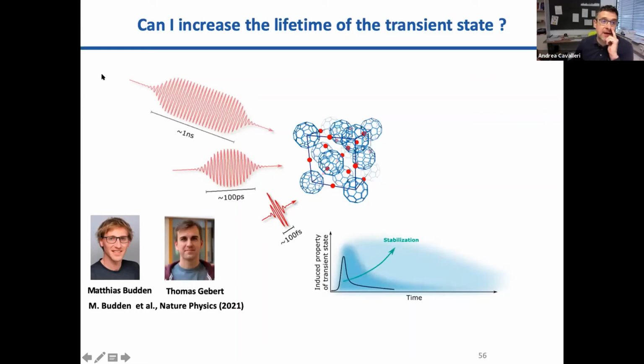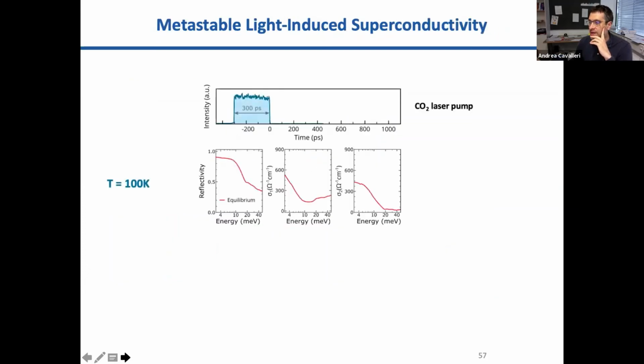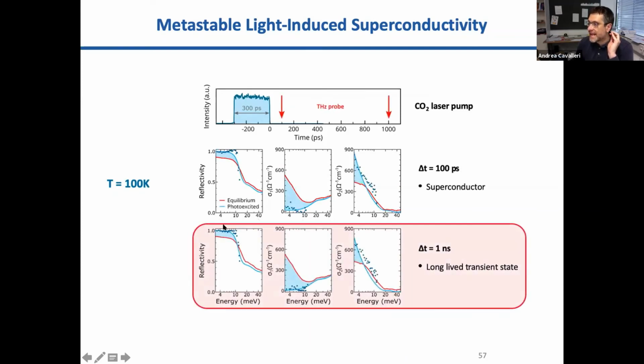This has to do with, I won't discuss how this was done, but this was the required development of new technology. Courtesy of German taxpayers' money, we were able to build a new laser that could drive the material for very long times. So what they discovered was that now, instead of driving the material with 1 picosecond pulses, we could drive it with pulses that were 300 picoseconds long, and they could reproduce the same superconducting-like features, reflectivity of 1, gap in sigma 1, and divergence in sigma 2, at far longer time delays than what I could observe before.